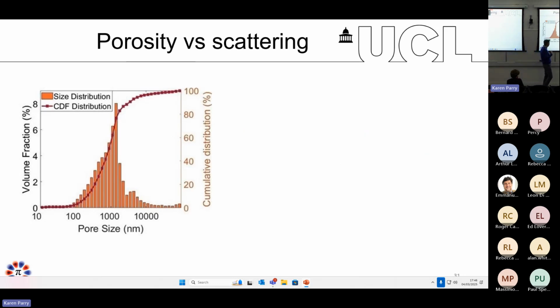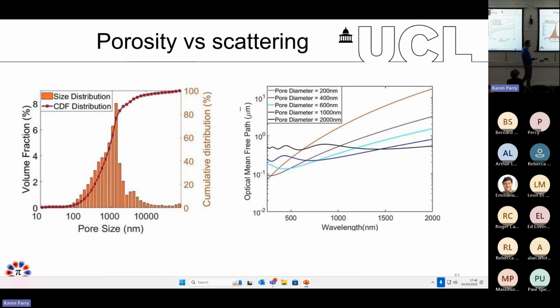Basically, the pores and the pore size are also very important because they determine how efficient the scattering process is. This is the pore size distribution as we characterized with mercury porosimetry. And this is the optical mean-free path as a function of wavelength. So essentially, the goal of any photonics engineer is to minimize the optical mean-free path. Optical mean-free path is the distance between subsequent scattering events. And if you have a very small distance, it means that you create a highly scattering and highly reflecting material with a minimum thickness. So you have gains in terms of cost, in terms of weight of the material, and so on.